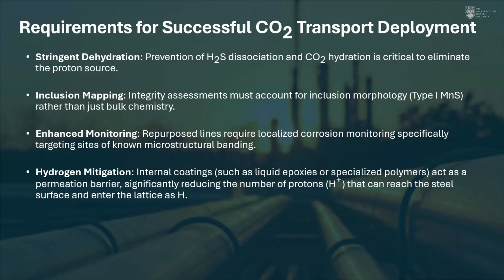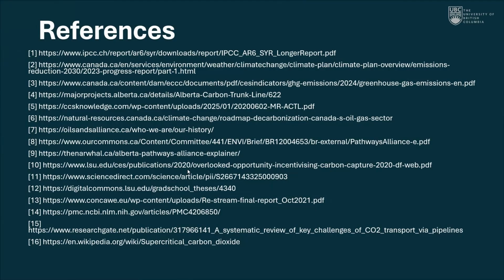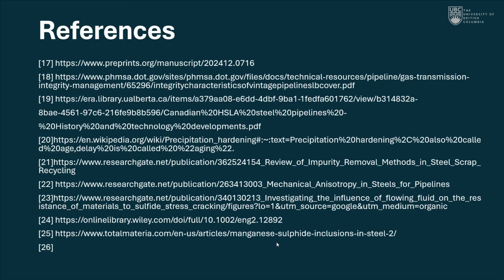What I found was a lot of carbon steels in the CO2 industry are in fact not having any internal coatings. They're bare steel. And so this, of course, is the biggest issue because if we want to prevent any hydrogen attack, we need a layer of coating to prevent that hydrogen diffusion through steel. So this concludes the research that I've done thus far. These are my references, and I hope it was informative enough to learn something new.